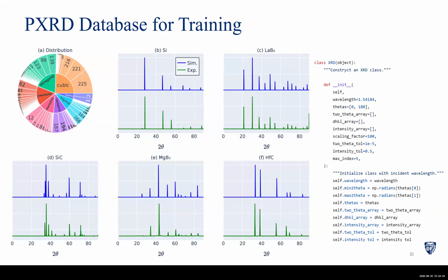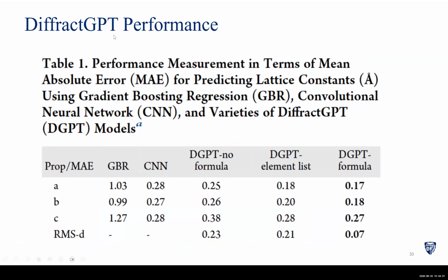So we took the JARVIS DFT dataset and made a powder X-ray diffraction pattern with this 20 lines of code. You can simulate powder X-ray diffraction quite easily. We took this dataset for all the 80,000 materials and generated a model called DiffractGPT, where the idea is if you have an X-ray diffraction pattern, a chemist will describe it as the following: I see a peak at 20 degrees with this intensity, I see a peak at 30 degrees at this intensity, and so on. So you convert a spectrum into text, in a language of how a chemist would describe it. That's your X, or input. Your output is your CIF file, like an atomic structure file, which is also text.